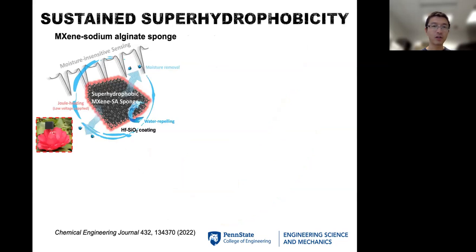But on the other side, we can also combine this idea to create a much more accurate sensor. For example, this super hydrophobic sensor can be very useful in highly humid conditions, but small moisture or water molecules can still condense on the microstructure and damage the super hydrophobic structure. So that's why here we combine that with the highly conductive MXene layer. That provides a way for us to drive just a small voltage and create local heating. And that Joule heating creates a very large temperature increase and drives off the moisture outside.